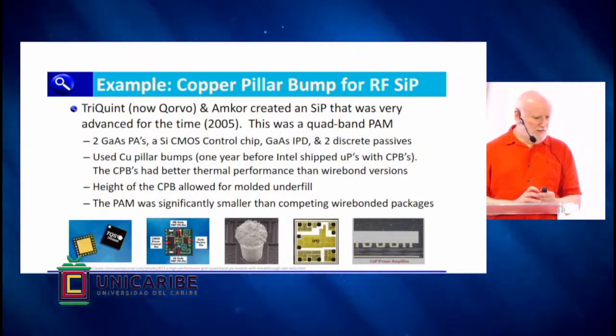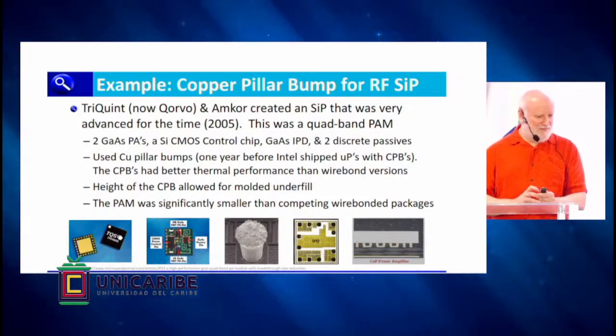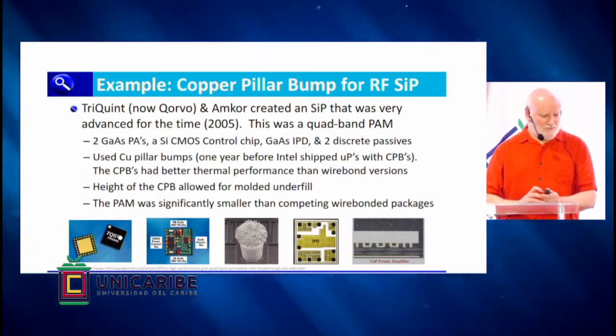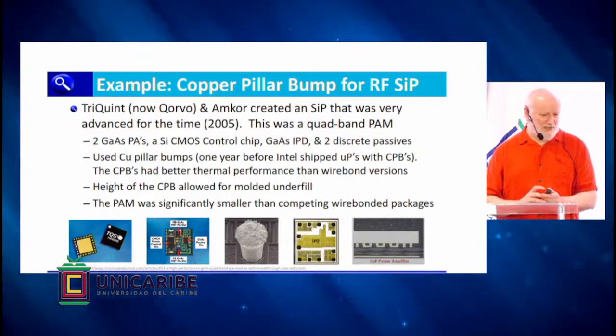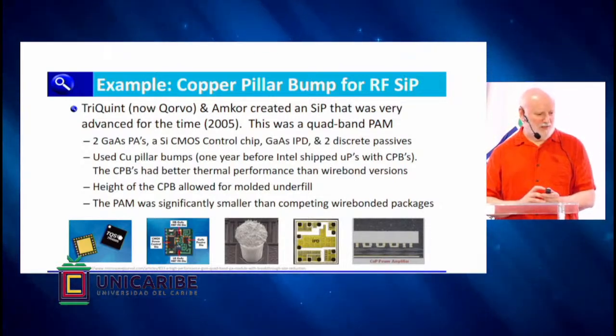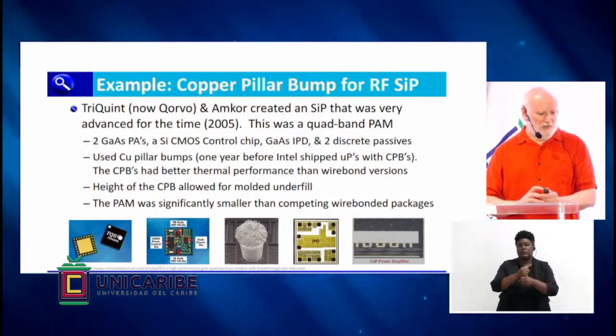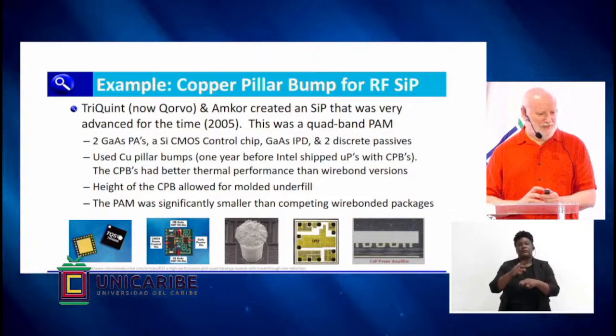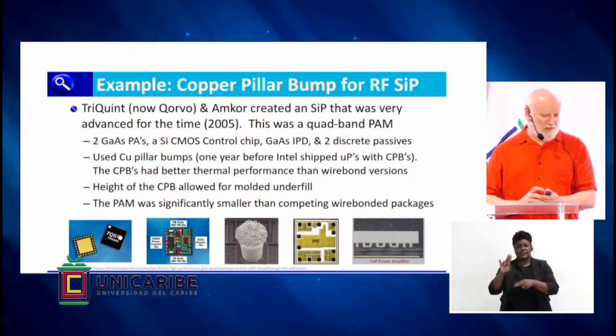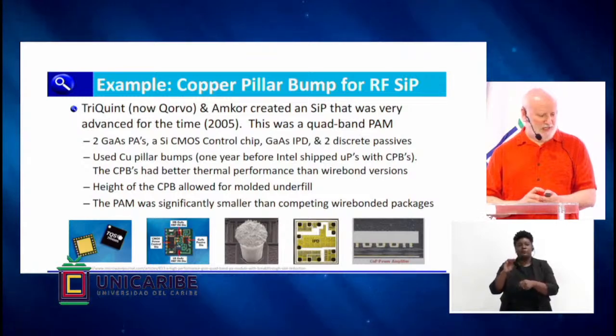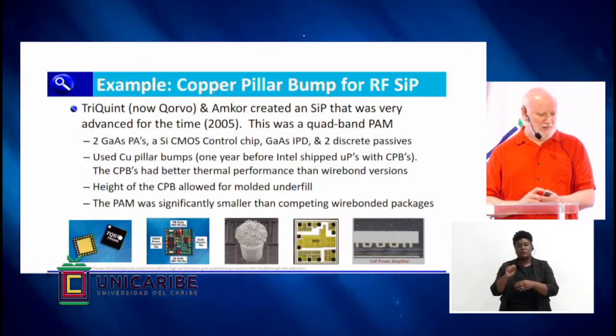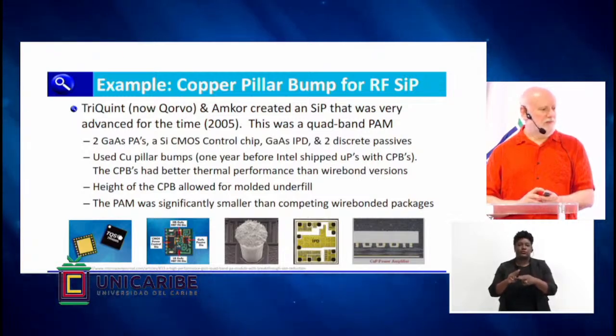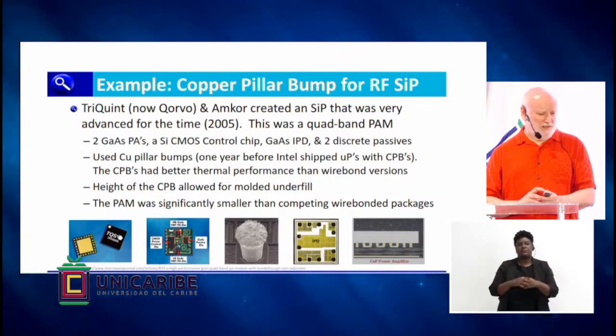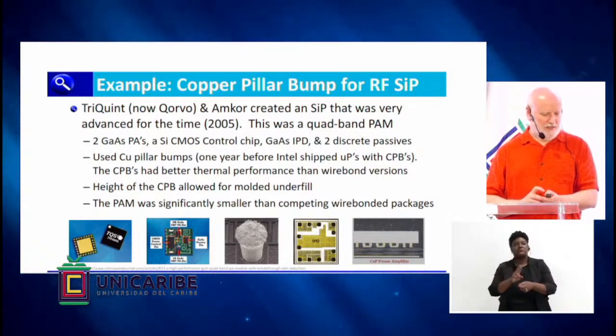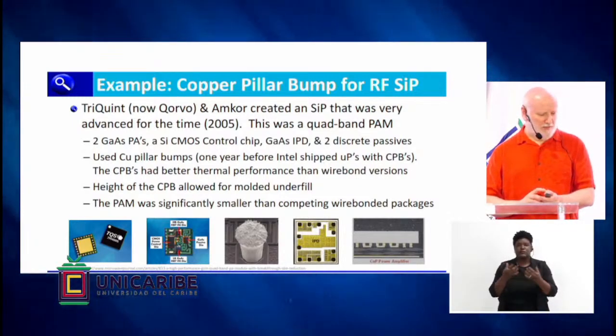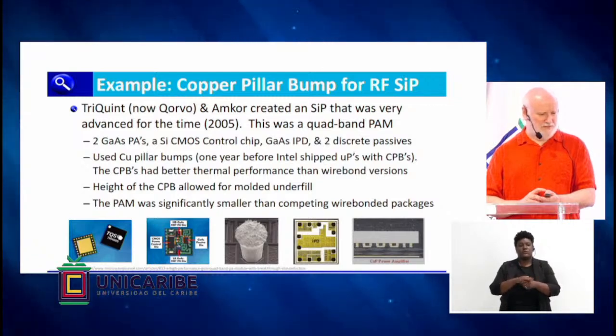Well, I had the opportunity to work on this project. This is back in 2005 with a company called TriQuint, now part of Qorvo. And we worked on copper pillar bumps back then, probably about 3 years before the industry really picked up on it. But what drove them to adopt copper pillar bumps was that they could get much better thermal performance than with wire bonds. And all the interconnect was contained within the footprint of the chip. So for them, they were able to shrink their part in comparison to competitors' parts.